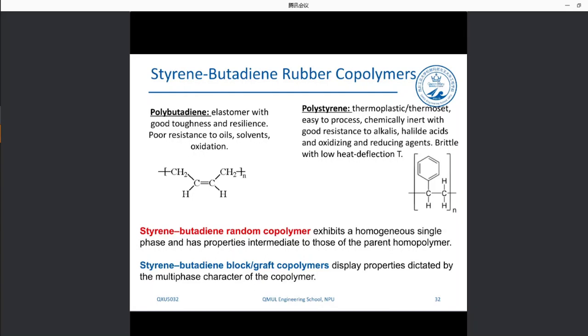Polybutadiene is a very, very soft elastomer. Because it is a very soft elastomer, it shows resilience, which is low modulus, or high flexibility. Good toughness. The toughness, as we said, is the area under the stress strain curve. So as you can realize, if we're able to extend our elastomer much more, we obtain good toughness. However, it has some negatives. It shows poor resistance to oil, solvents, and oxidation. That is because it has very low or zero crystallinity.